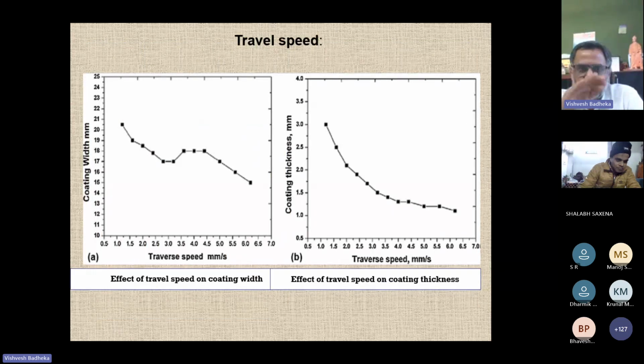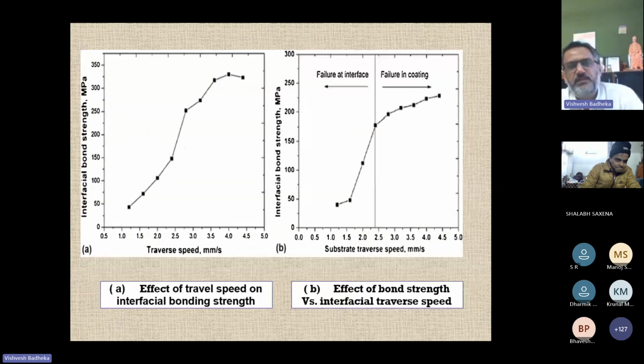Similarly, as your travel speed increases, meaning the substrate is going to move faster, what will happen? Your coating width will go down. The thickness of the coating also will go down. As in arc welding processes also, as your welding speed increases, your reinforcement will go down and bead width will go down, because your heat input is also decreasing. Similarly here also, the width of the bead which you are depositing will go down, and coating thickness also will go down with increasing travel speed.